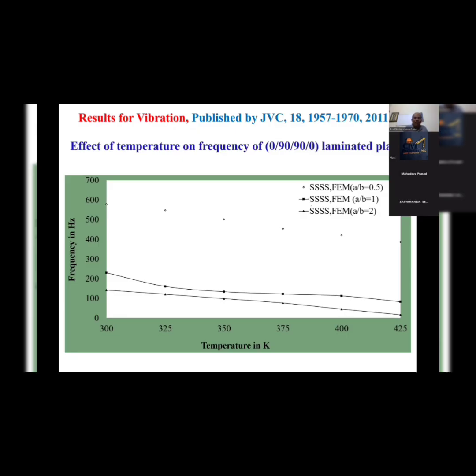Then effect of temperature. With temperature, the frequency decreases. This is in Kelvin: 300 Kelvin, 325 Kelvin. 300 Kelvin means normal temperature. Then we increased by 25, 50, 75, 100, 125. As you can see, the frequency decreases with the increase of temperature.